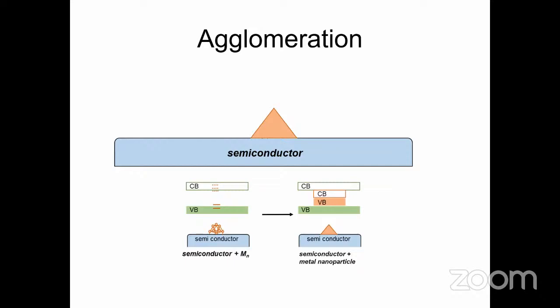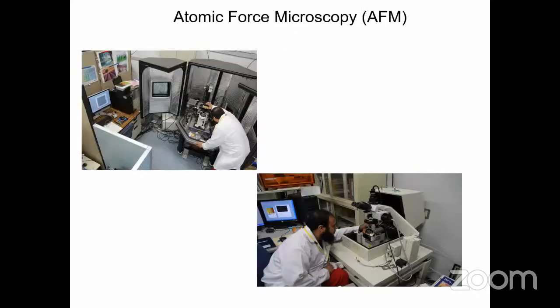in the reaction itself. And to measure this agglomeration, we need scanning probe microscopy, like atomic force microscope and STM, scanning tunneling microscope, to measure the degree of aggregation when we deposit them on the metal oxide itself. We deposit them on titania nanosheet, and we check before annealing and after annealing.